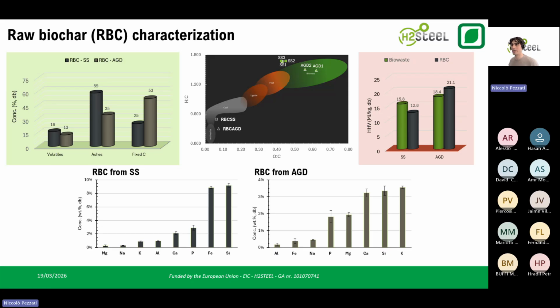The most relevant aspect here, though, is the increase of the ash content. In particular, in the case of processing the sewage sludge, we almost touch 60% ash content in the raw biochar, which is a shortcoming of this first stage, but which we can fix later through the chemical leaching.